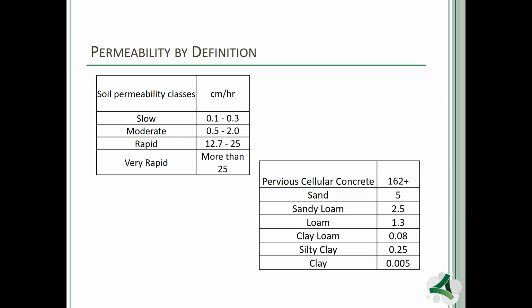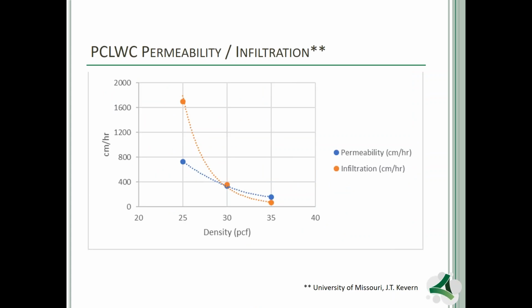Pervious cellular concrete is extremely pervious. It starts at 162 centimeters an hour and goes up from there. With pervious cellular concrete and its permeability, we see the best permeability between 25 and 35 pounds per cubic foot. Once we increase the density, we start losing that permeability. So that's why we generally see pervious cellular concrete placed between 25 and 35 pounds per cubic foot.